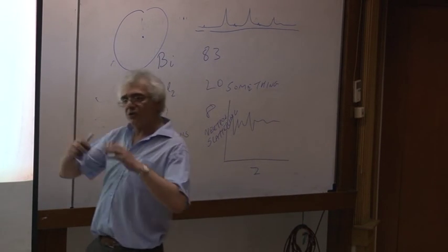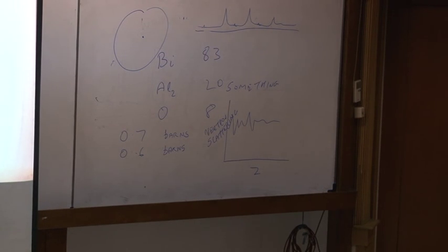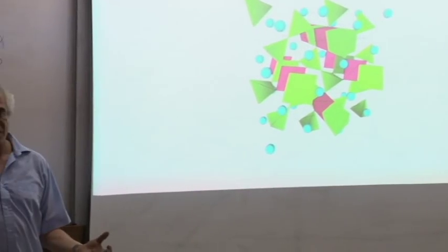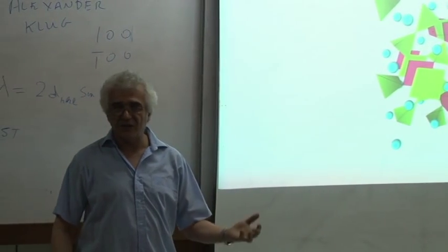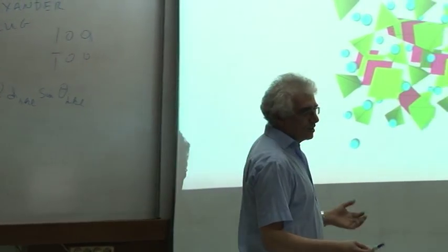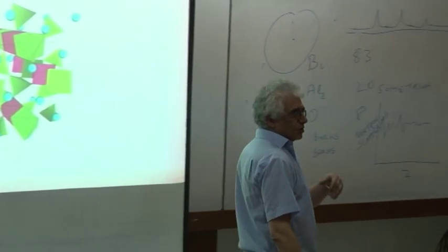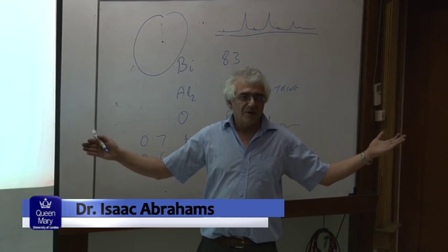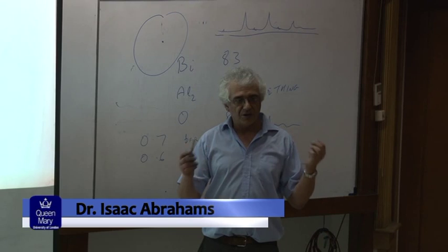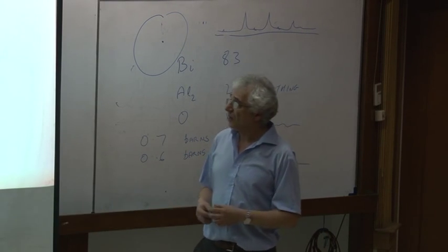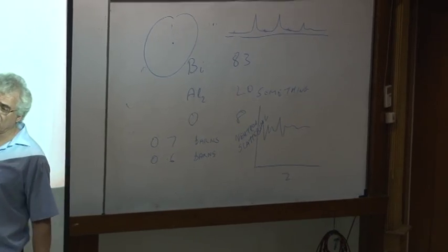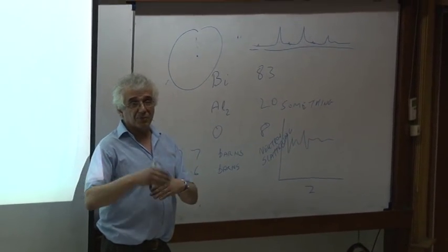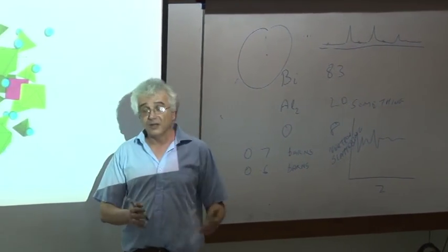And it means that the oxygen is more clearly defined, and if we're looking at oxide ion conductors, we're very interested in what the oxygens are doing. Similarly, things like lithium ion conductors, those of you who might be doing work on batteries. Lithium, very small, atomic number 3, in X-rays it's virtually invisible. So if you want to look at the lithium, see what it's doing in the structure, you have to use neutrons. So you can do something like this. You can take the X-rays to give you good positions for your heavy atoms, and neutrons to give you good positions for your light atoms, and together you get a very nice structure.